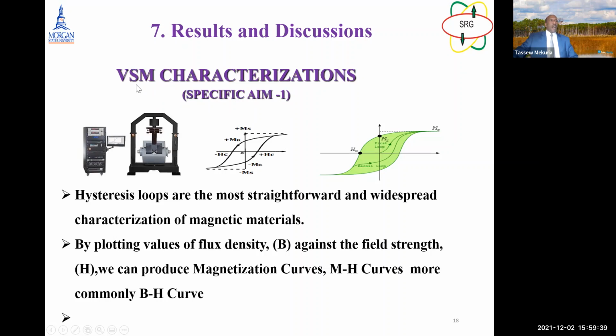I start with a specific aim 1 VSM characterization, and this is magnetization. We try to plot the hysteresis loop because it is a straightforward and widespread characterization of magnetic material. By plotting values of flux density B against the field strength H, we can produce the magnetization curve, or MH curve, more commonly known as the BH curve. So we tried to see how magnetization changes as a pristine sample, when the tube is intercalated, and when chromium is dispersed on them.